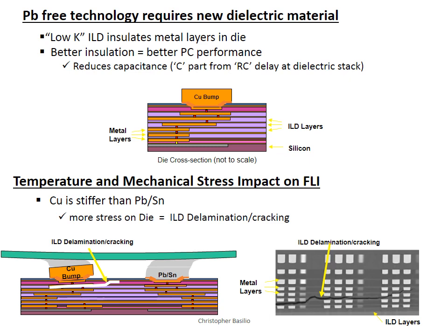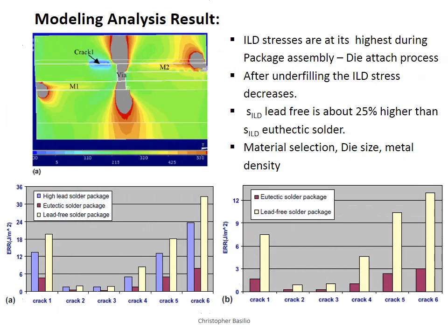The flip chip packaging plays an important role in the silicon package interaction. Based on this study using FEA and Moire analysis, it was determined that the ILD stress is at its peak during the flip chip assembly process, particularly during the die attach. The table below shows the energy release rate of a lead-free package in comparison to a eutectic and high-lead solder package in the die attach process.